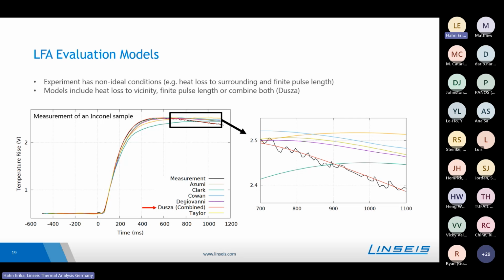As mentioned before, we find out the thermal diffusivity using this temperature rise with time curve. It is not as simple as just doing it graphically as indicated in some slides before, but for the evaluation, we use some models. And the basic model would be the adiabatic model, describing the heat transfer or heat transport within a material. However, the adiabatic model assumes the ideal case, but in reality, typically this cannot be fulfilled. So there are some corrections which need to be done, which is in the case of the laser flash, mainly the heat loss from the sample to the sample holder or the surrounding, as well as some finite pulse length effects, especially for fast and thin samples.